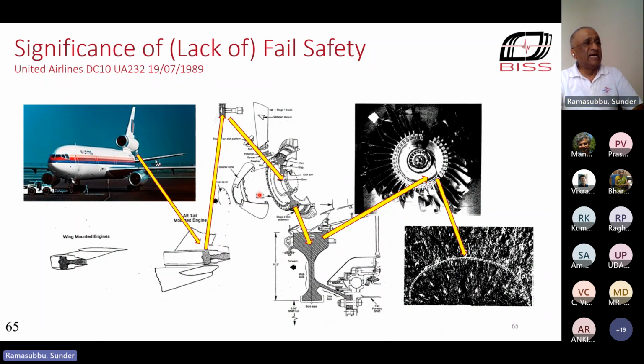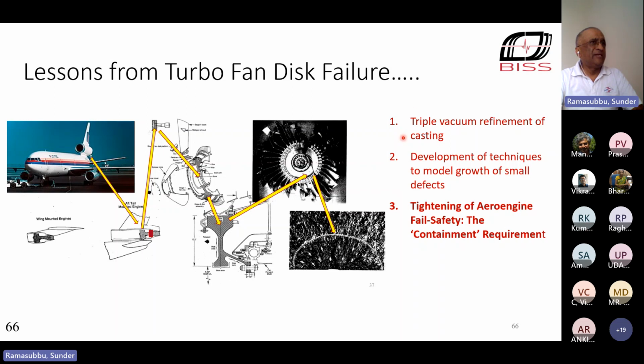And that failure was traced to a small 25 micron defect in the titanium disc. So the consequence of that was triple vacuum refinement of casting. Today, we don't have those defects anymore. And the introduction of a fail safety requirement of containment. So today, you cannot develop an engine if you cannot demonstrate that when something breaks inside, the engine will not explode.